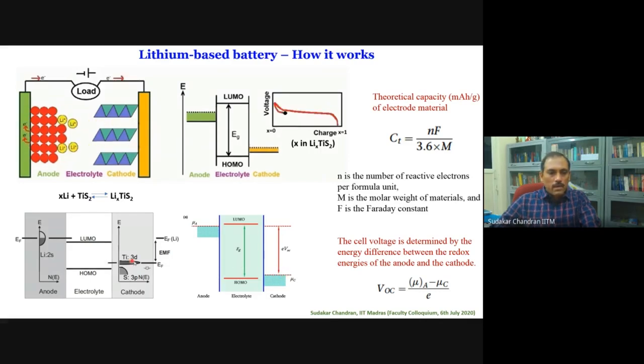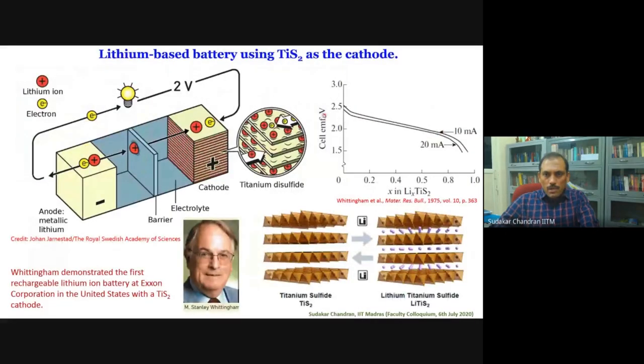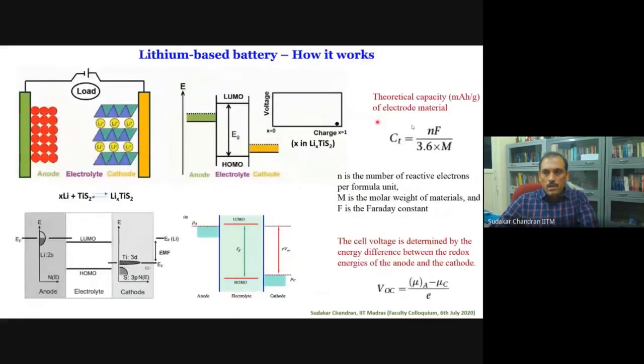In the case of titanium disulfide, the Fermi energy of titanium is in the titanium 3d orbitals and 3d energy levels. And then the Fermi energy of lithium is here. So that gives the voltage. The voltage you get in titanium disulfide is 2.5 volt, and this is the largest voltage they could get with any of the sulfides as the cathode.